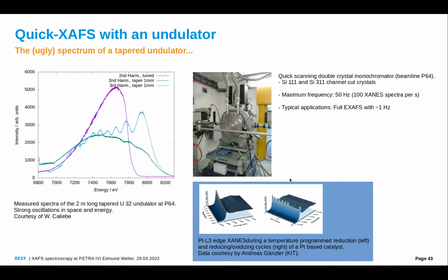The second reason why an undulator is a bit problematic is the fact that it's emitting a very narrow spectrum in the undulator peaks. And in order to broaden the spectrum to do XAFS spectroscopy, we use tapering of the undulator. But this is not without problems. You see that there are oscillations when you move in energy, and these are not only oscillations of the intensity. This would cancel out on a good beamline with good ionization chambers. We calculate I1 over I0. Actually, there are also spatial intensity fluctuations, and then again you probe the homogeneity of your sample and not so much the XAFS. So this comes with some problems.